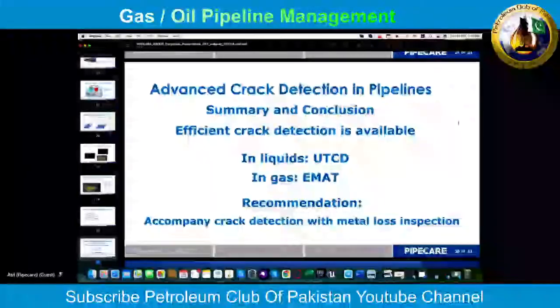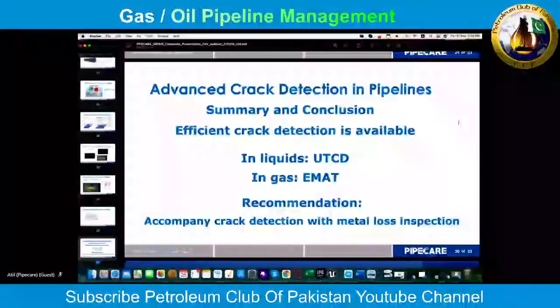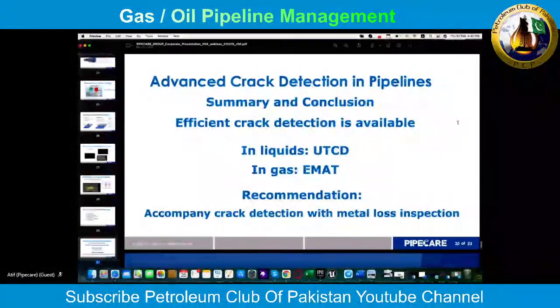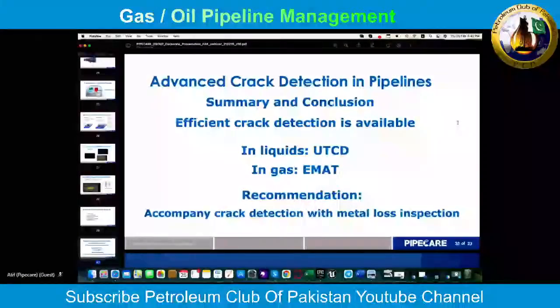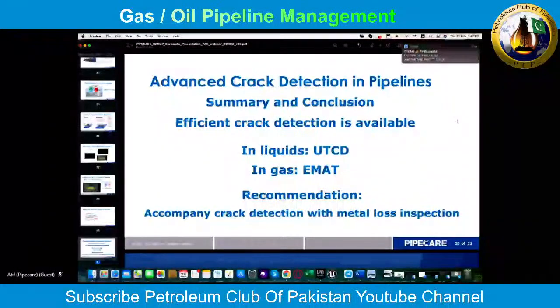Metal loss features, general corrosion, is a random process, and these features may develop sharp edges. And the sharp edge may be interpreted by the ultrasonic crack detection tool, and therefore the analyst, as a crack or a crack-like feature. And in order to avoid false positives, meaning that we declare that a feature is a crack, and the customer goes out into the field, digs up this location, and finds that it is a metal loss feature instead of a crack. This is a false positive, and this is what we want to avoid. And in order to help the data analysts, a metal loss inspection will help tremendously.